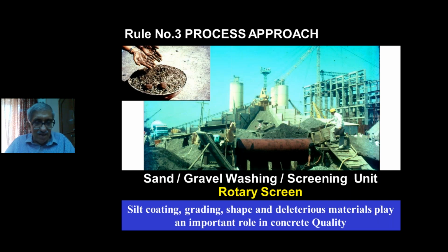But gravel was being used at the batching mixing plant, and because of the clay coming in the gravel, it was developing a silt coating, and therefore the quality suffered like anything. It was very difficult to achieve M20 grade concrete, meaning 200 kg per centimeter square strength concrete, because of the coating.